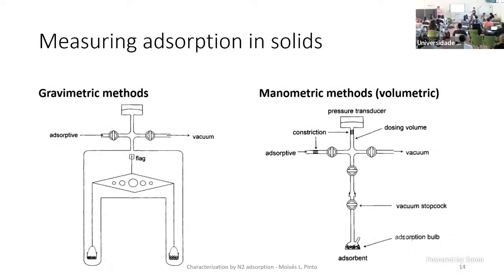So there are two big types of methods. One is the gravimetric method. As you understand here, you have a closed balance that is attached to a vacuum system, and where we can introduce some vapor of an organic molecule or a gas. And then we record the weight increase over time, and when it is stable, we pick up this value as an equilibrium value, and this is a point in your isotherm. Of course, you need to have a pressure gauge, a pressure sensor. So we record amounts adsorbed as a function of pressure.